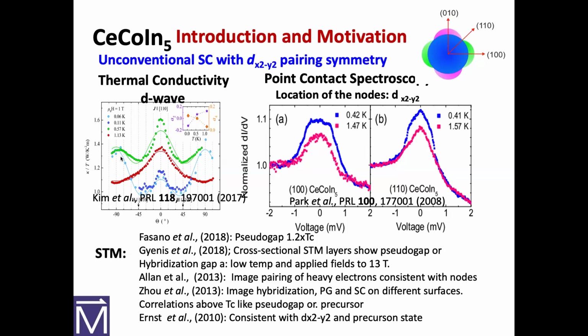And basically, we understand that. If you want an explanation that's not quite right, but will satisfy you phenomenologically: the one on the left, if you imagine going into the 100, 010, it looks like an S-wave superconductor. If you're going in the 110, you see that it goes down to a point, and that's what you measure. You can actually do that mathematically. Okay? So any other questions, please bring them up.